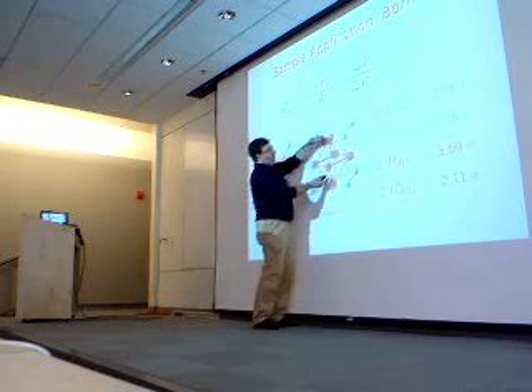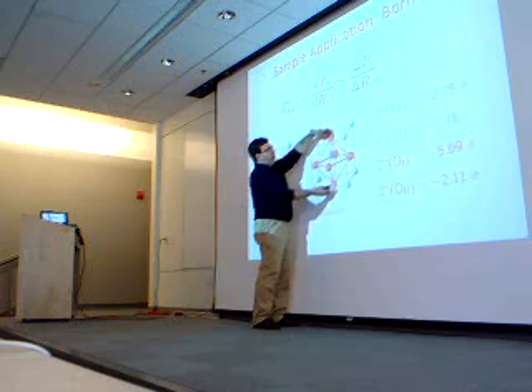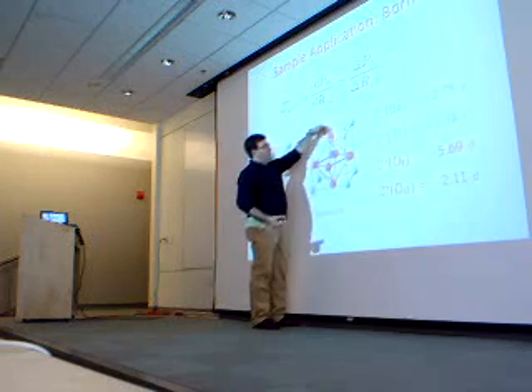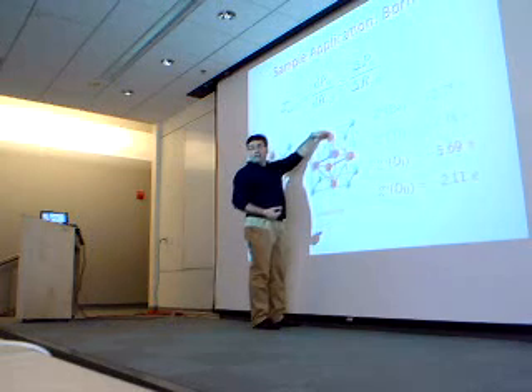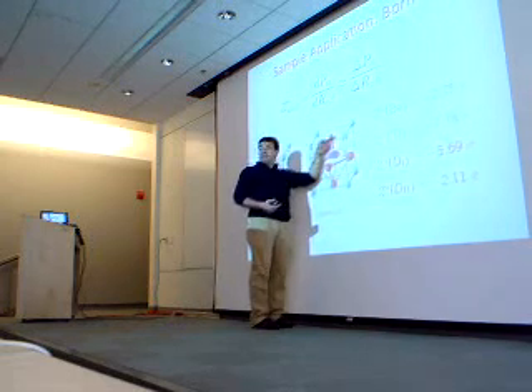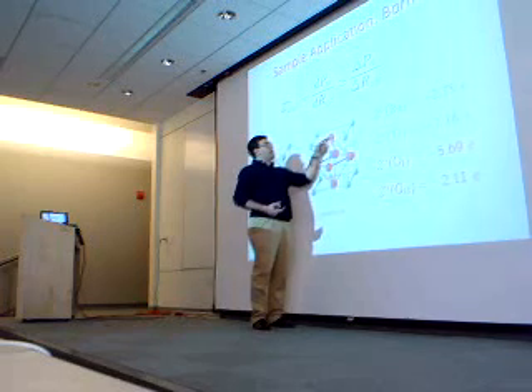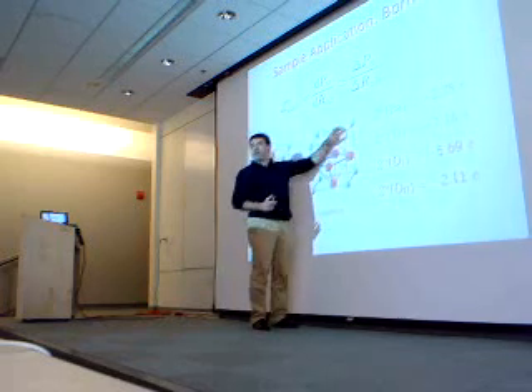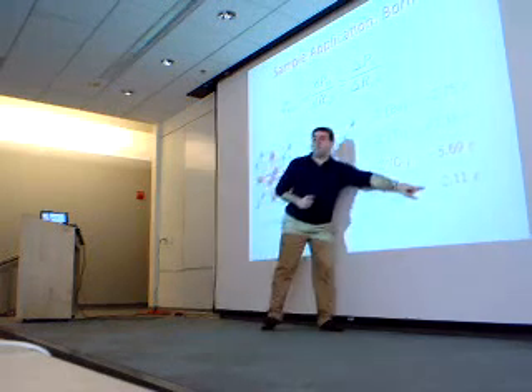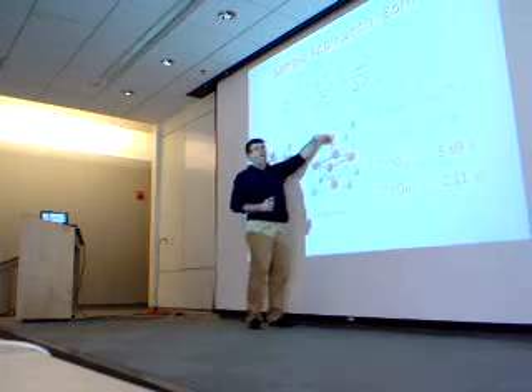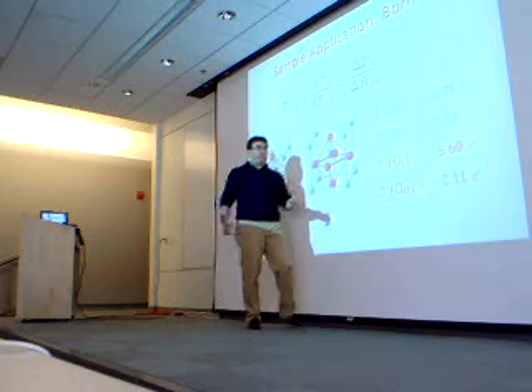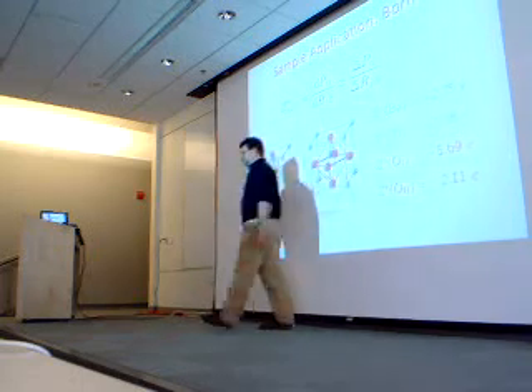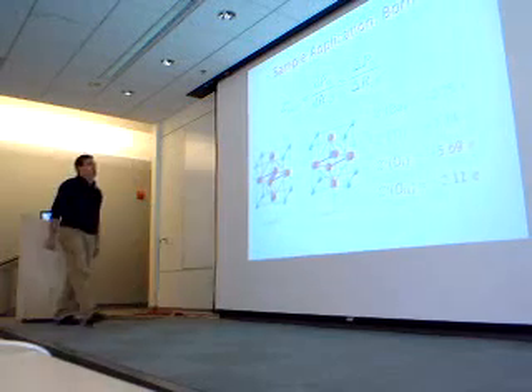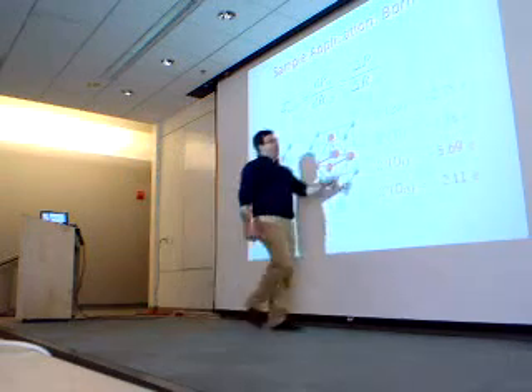And actually, for the ferroelectric material in this configuration, the effective charges of the oxygen are large in this direction, but are fairly trivial in this direction. Because when you move against this, you're sort of in an oxide plane against the barium, and so you look very much like an oxide. But when you move against the titanium, you are shifting a lot of charge, and so the effective charges are huge.